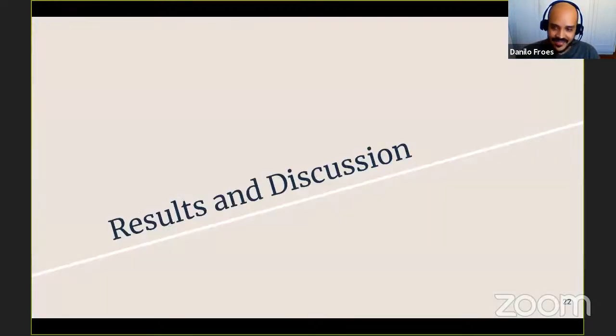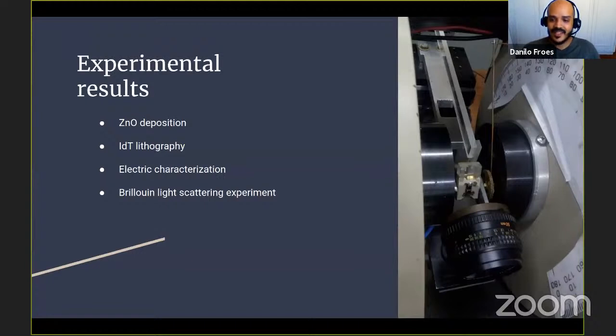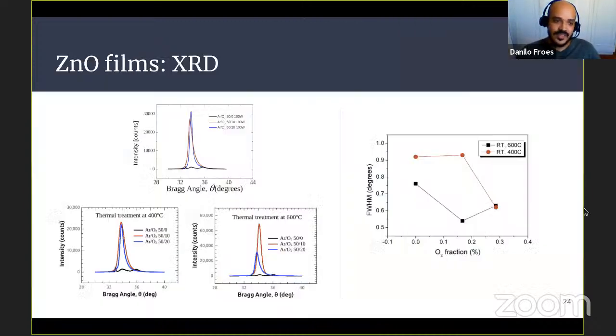Okay, so speaking of the results now, the experimental results. Here is a picture of the Brillouin light scattering equipment. Here is our angle measurement, a very technological angle measurement system, this thing here. So we started by depositing ZnO by radio frequency magnetron sputtering. Here I'm just showing the spectrum of the X-ray diffraction. Without oxygen is the black one. We didn't have the 002 orientation, but when we employed oxygen, we started having this. So we're trying to improve the quality of the ZnO, the zinc oxide we deposited.